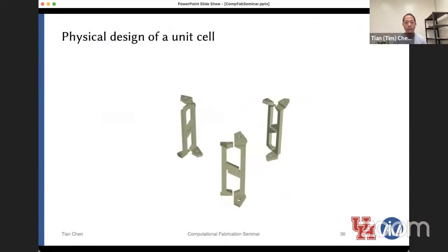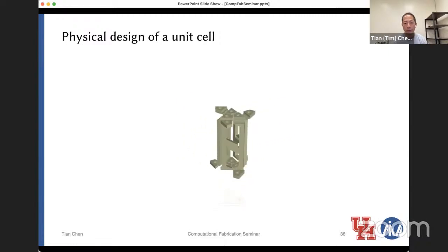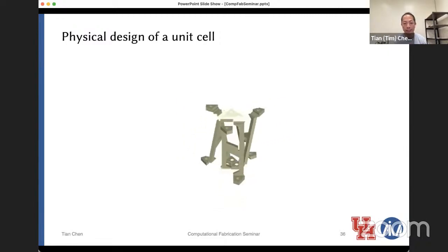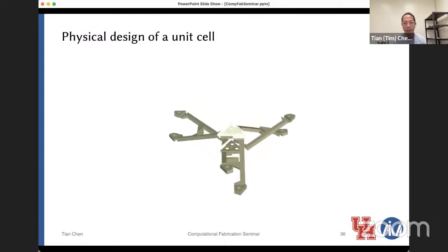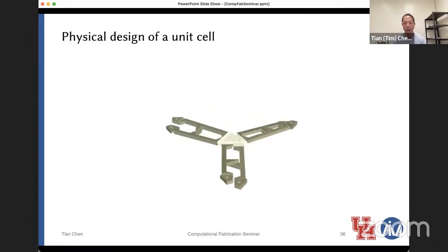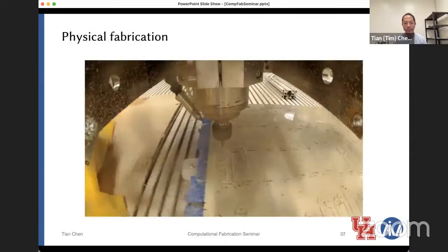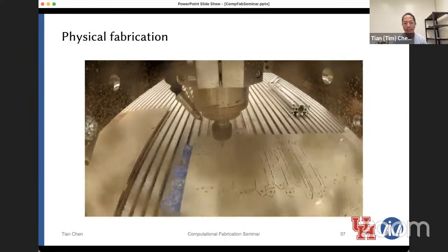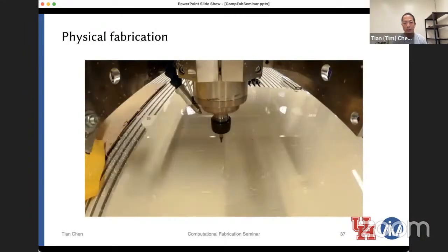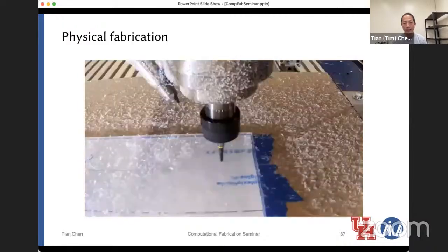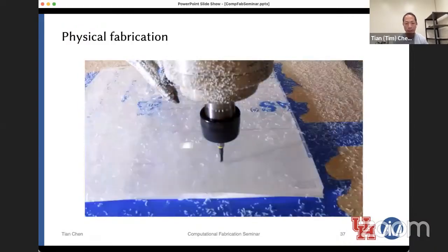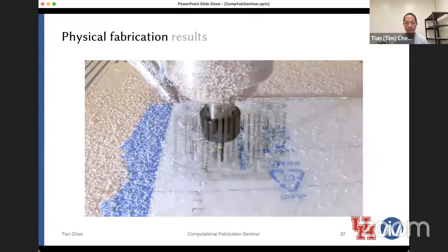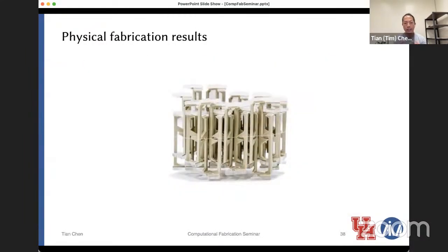Now we move to the physical design of the unit cell. We cut these scissor mechanisms and attach the top and bottom plate. You see this is the transformation that happens through these live hinges or elastic joints. The fabrication is, again, planar and very simple. We use a milling tool that's able to fabricate using polypropylene as material. We assemble these manually to create the compact state, and then we deploy this into the 3D state.